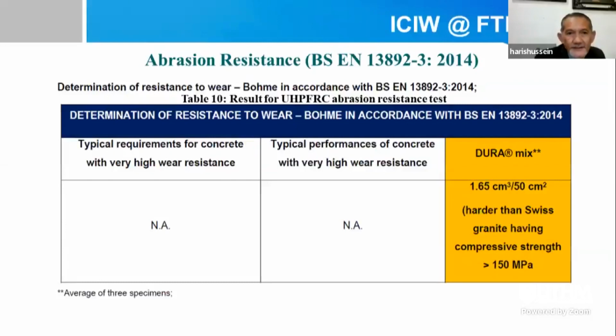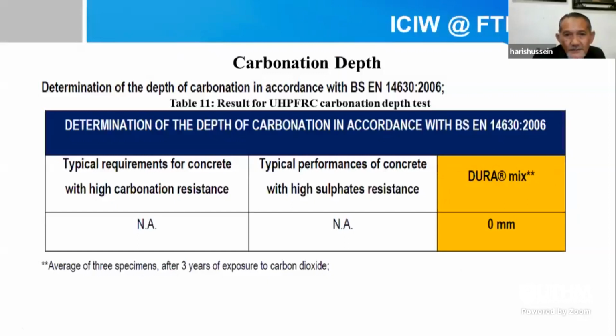For the abrasion test, resistance complied with the standard, and carbonation depth is 0 mm, which means no penetration for carbonation.